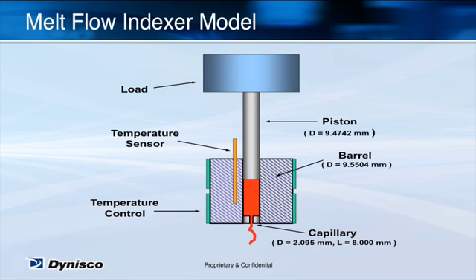Because of the short capillary L over D, this rheometer measures not only viscous losses in the capillary, but also viscoelastic losses in the capillary entrance. This means that the measurement is a function of both the rheometer geometry as well as the polymer viscosity. In other words, the ASTM D1238 standard defines both the apparatus and the polymer test conditions.